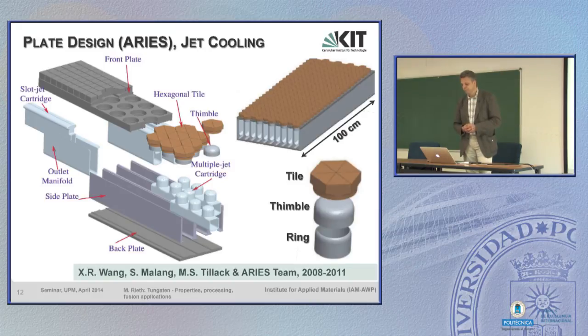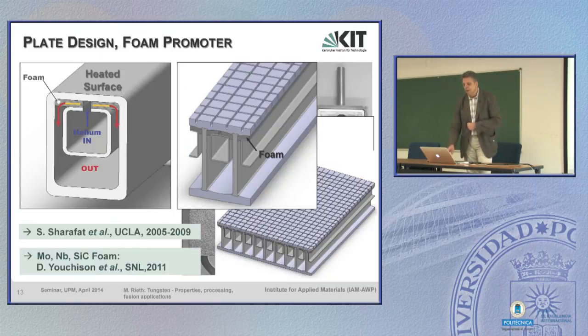There are some other design ideas which make use of tungsten, or which try to fabricate such divertor blades completely out of tungsten with cooling channels, all made of tungsten blades. They have to be brazed together in some way. They also use these jet cooling cartridges, and they also use tungsten as an armor part on top in many different ways. Another idea is to use, again, tungsten as a cooling structure in the form of a pipe. Then to increase the cooling area, a metallic foam is inserted here, and helium is pressed through this foam also to remove heat.